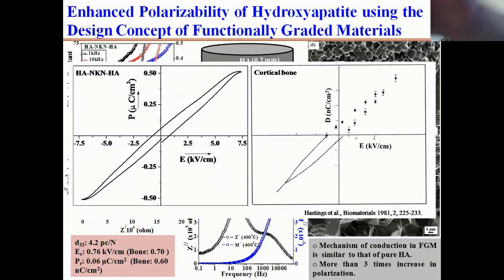So you can see this left hand side is the piezoelectric hysteresis loop for this developed functionally graded material, and right hand side is just for the cortical bone sample. This cortical bone sample means hard bone sample, because we have two different types, as we saw, the cortical and cancellous. The cortical one is very easy to measure, right, because they are very hard bones. So you can see this is very comparable to that of the bone sample. So you can develop electrically active hydroxyapatite. So this is one of the aspects that I said in the beginning, that one of the aspects is to develop functionally graded materials for biomedical applications.